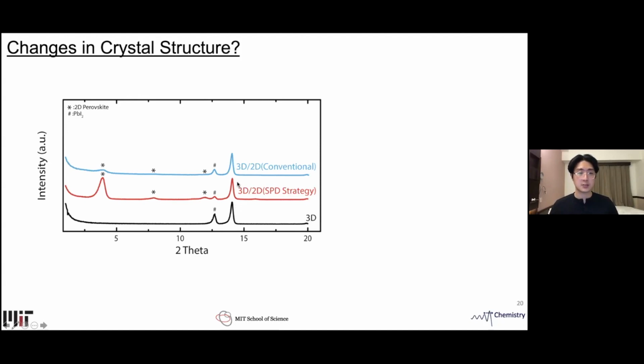The two traces shown in blue and red are the 3D/2D heterostructure prepared using the conventional method and the SPD strategy. Here we see that with the heterostructure, there is an evolution of new peaks in the lower 2 theta range, suggesting formation of a crystal structure with a larger lattice constant, which we assign to the 2D perovskites.